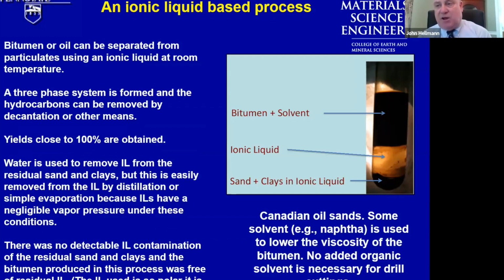The bitumen and some solvents are shown in the upper layer. The ionic liquids are in the middle. And then the sediment at the bottom are the sands and clays. Now, in the case of tar sand separation, this is desirable. You extract the bitumen and use it. In our case, it's also desirable, but we would be extracting the sand and clay and using that. Fortunately, the ionic liquid separation process works well on drill cuttings.